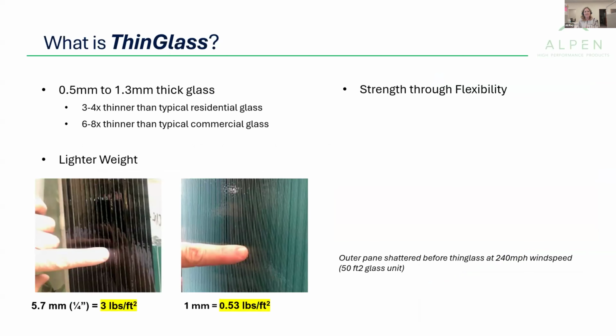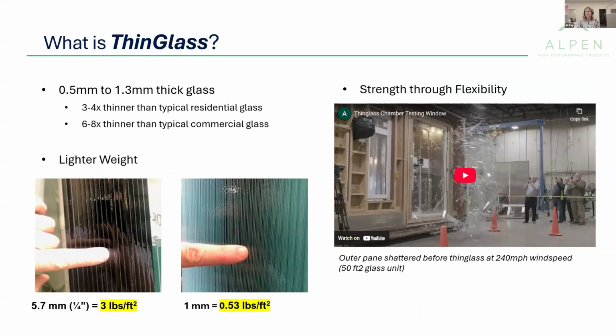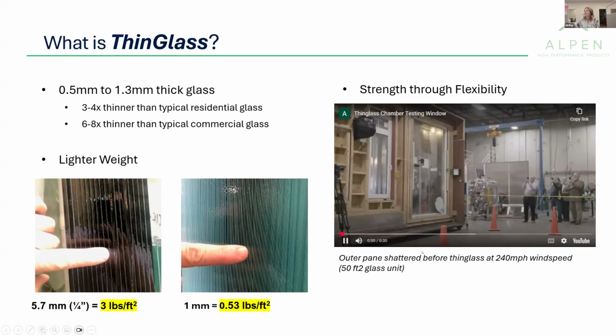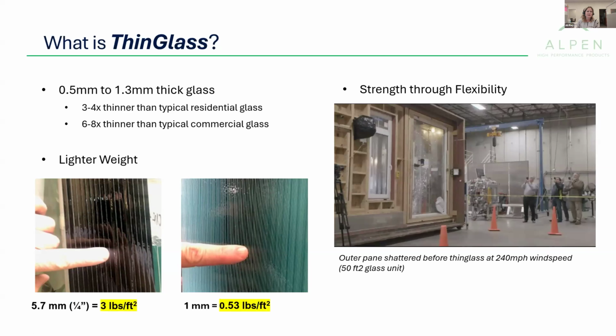So what is thin glass? Thin glass is 0.5 millimeters to 1.3 millimeters thick. It is lighter weight than traditional glass because it is about 3 to 4 times thinner than typical residential glass and 6 to 8 times thinner than typical commercial glass. We can take a 1/4 inch commercial unit, which is 3 pounds per square foot, and cut that weight down to about 1/2 pound per square foot.